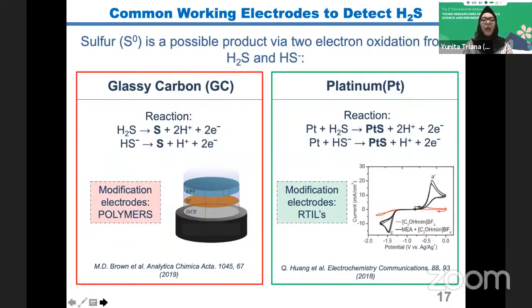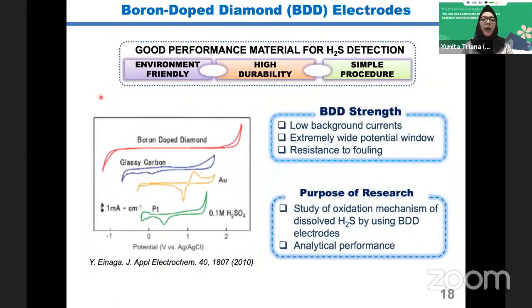And in this research, I will use a boron doped diamond electrode, because we believe that BDD is environmentally friendly, has high durability, and offers a simple procedure to detect hydrogen sulfide. And this is a paper that shows the potential window compared with glassy carbon, gold, and also Pt. So BDD has the widest potential window.